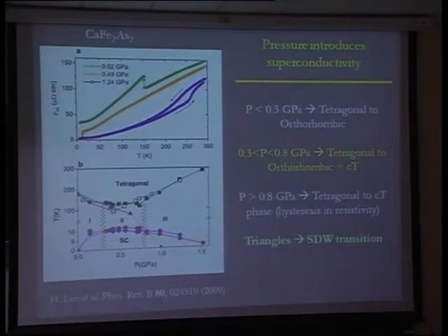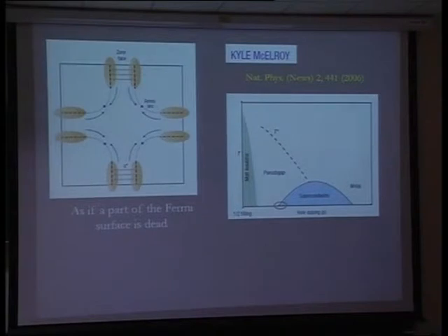So here you have this tetragonal to orthorhombic phase transition. In this region, you have a mixed kind of structural phase, so it's orthorhombic plus what is called collapsed tetragonal phase. So it's maybe tetragonal like, okay? And the transition temperature goes down gradually if you apply pressure. So you can see that in the high TC phase, if you compare with the typical phase diagram that people often go for, you vary a certain parameter here and you get a superconducting dome. So it looks like this calcium iron arsenic two also resides somewhere close to this region. So that gives you an analogy. Okay, so that's the thing.